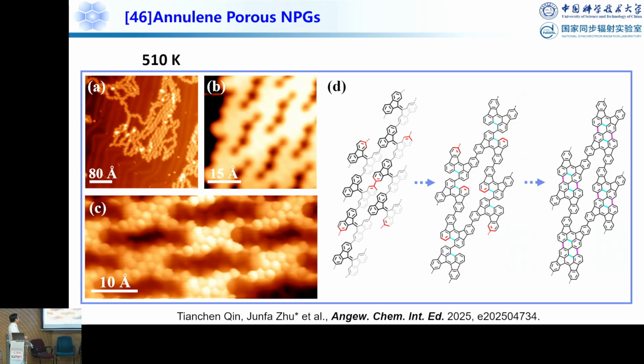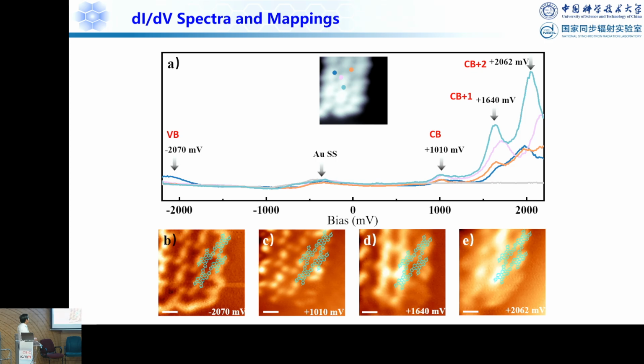Then we further increase the temperature, and now you form this structure. A cyclodehydrogenation reaction happens in many of these molecules. Now this pushes towards this direction and then opens up, and the atomic-resolution STM results tell it is the truth. It is like this, and Jimin Cai also observed a similar structure. And this is the whole structure measured from dI/dV spectra and mapping, and it tells you that this is the valence band and this is the conduction band, and they do have these electronic properties at this voltage.